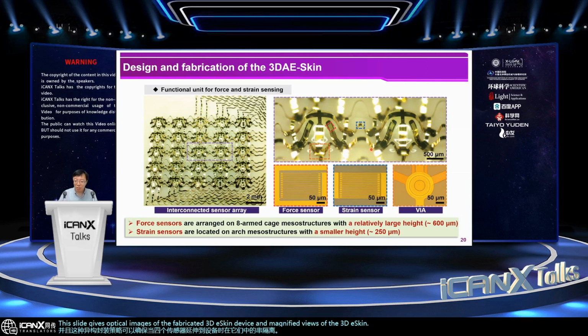Okay, this slide gives optical images of the fabricated 3D e-skin device and magnified views of the functional units and the force sensors, strain sensors, and the vertical interconnect access holes. So it's obvious that the force sensors are arranged on each arm of the cage mesostructure. And the cage mesostructure has a height of 600 microns. In comparison, the strain sensors are arranged on top of the arc mesostructures, which just has a height of 250 microns. So such a height difference ensures that the force sensors are much closer to the skin surface.